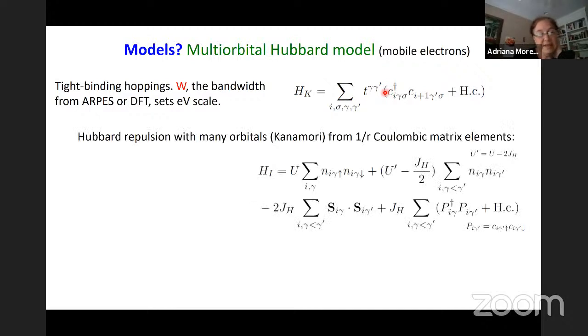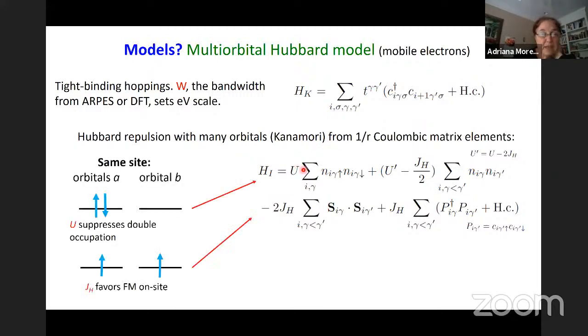Then comes the interaction terms, where we have a Hubbard repulsion with many orbitals, and the terms come from the 1/r Coulombic matrix elements that were obtained by Kanamori in the 50s. So the main interactions are the Coulomb repulsion, on-site Coulomb repulsion, that suppresses the double occupancy of electrons in the same orbital in the same site.